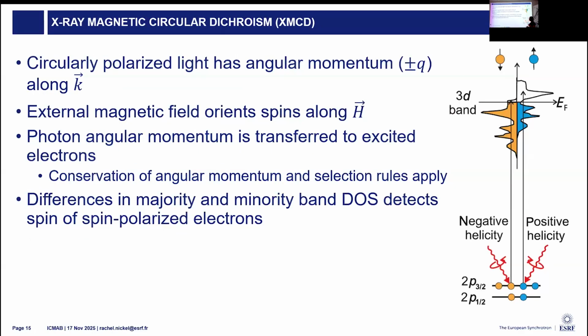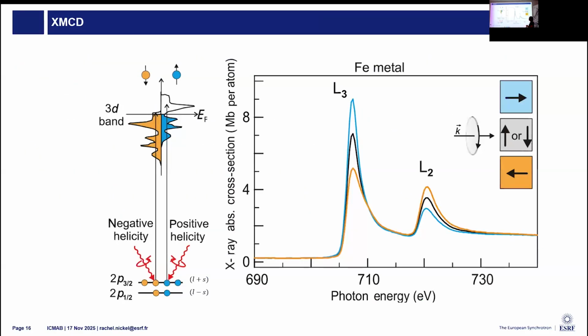We can use the polarization of light to probe these differences using X-ray magnetic circular dichroism, where we align the moments with a magnetic field along the propagation of the beam, and then we use circularly polarized light, which has an angular momentum, to excite into the empty hole states. In practice, what this means is we get a dichroism and a difference that shows because left polarized light, which has a negative angular momentum, will excite electrons differently than the right polarized light.